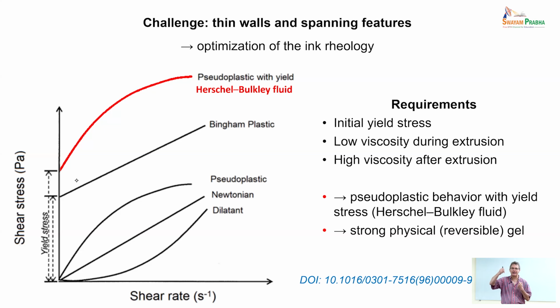So the fluid has a yield stress. You need to apply a stress above a certain threshold. Then you apply the stress and the viscosity decreases, and then it starts flowing. But once the fluid comes out of the nozzle, the viscosity increases because the stress is decreased. And therefore, if you have the bristles of your toothbrush, the toothpaste sits on top, doesn't flow a lot into your bristles. So for your ceramic feedstock, you need to engineer that type of rheology. You need to have a yield stress and you need to have a pseudoplastic behavior.